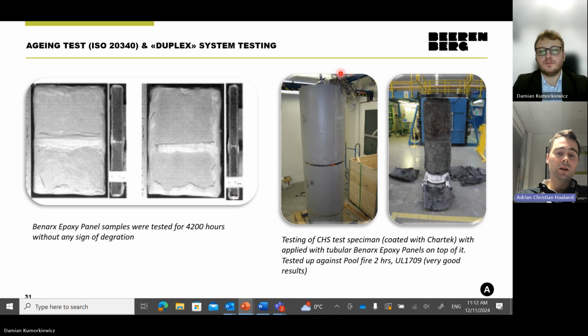We do some testing on environmental exposure, so typical paint type top coat testing against weathering tests, the aging tests. And we also do some customized fire tests for a hybrid system where we have our system as a repair system over existing or damaged PFP, as you see on the right here.